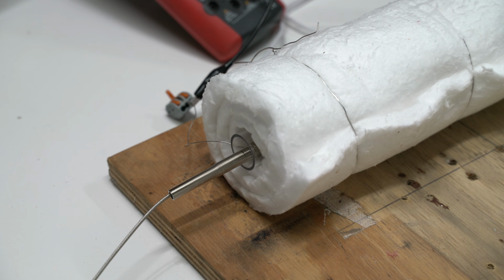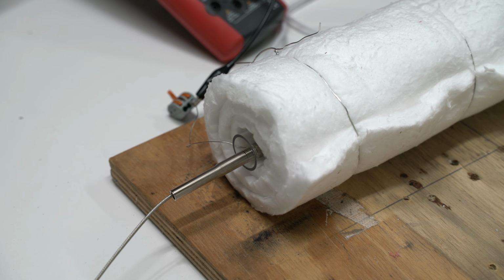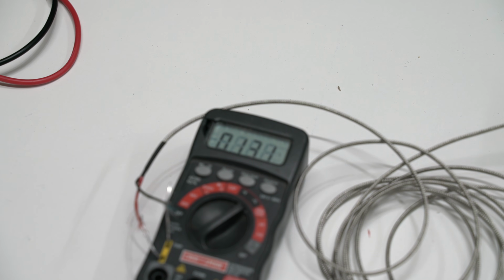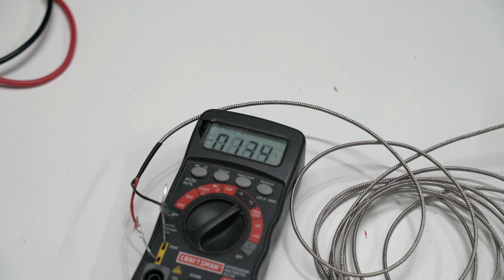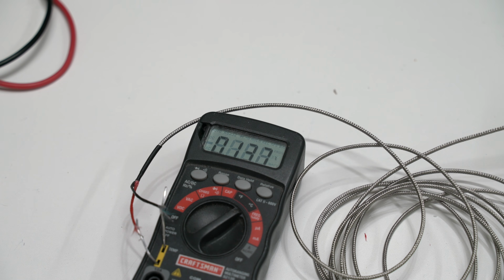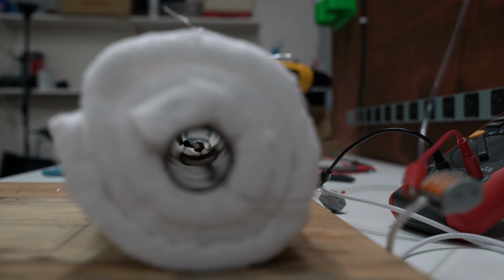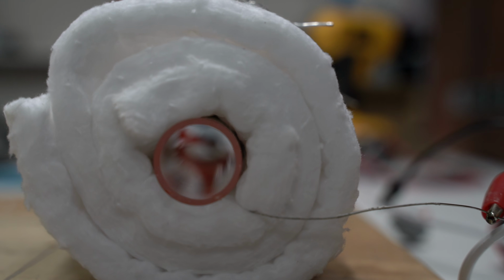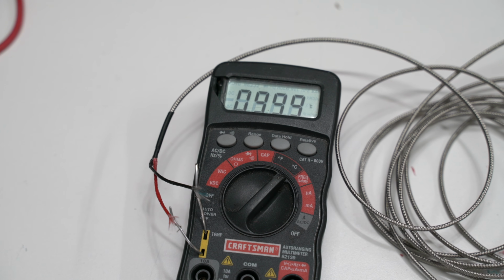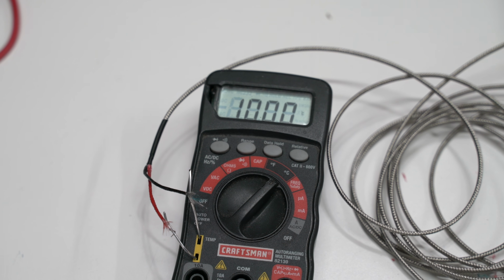I inserted a high-temperature thermocouple directly into the tube to keep track of how fast the temperature is rising. For a quartz tube, it's important to keep the temperature ramp rate to about 30 degrees Celsius per minute maximum. This is a little faster than I would like. For a while, it won't really look like anything is happening, but at around 600 degrees Celsius, you'll start to see a slight orange glow coming from the tube. After about 30 minutes of heating, I finally reached 1000 degrees Celsius.